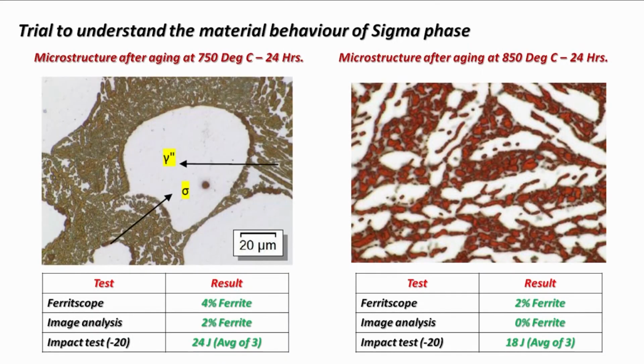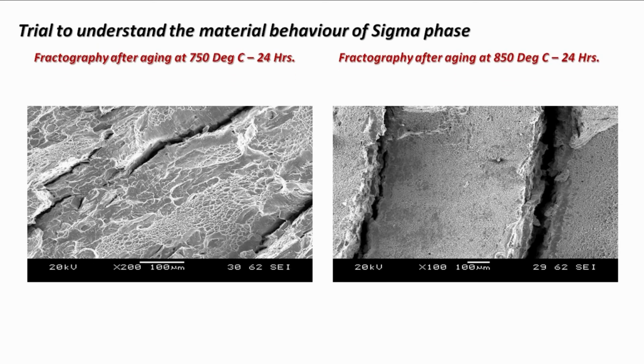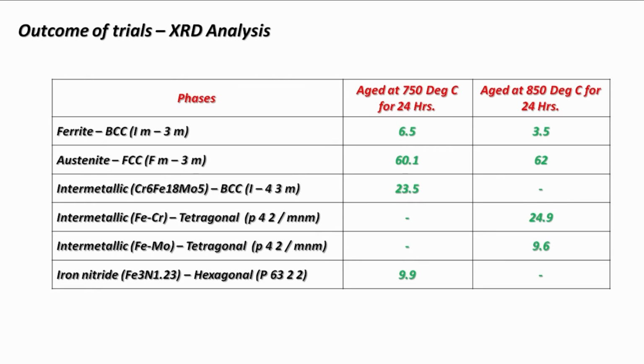So you can see at 750 degrees Celsius, the secondary phase formed is much finer than the secondary phases formed at 850 degrees Celsius. And the fractography image shows clear brittle fracture. So further we did some XRD analysis and we understood that at 750 degrees Celsius, the secondary phase that forms is actually not sigma phase, it is chi phase, which has a BCC crystal structure. Whereas at 850 degrees Celsius, the secondary phase formed has a tetragonal structure, which is sigma phase.